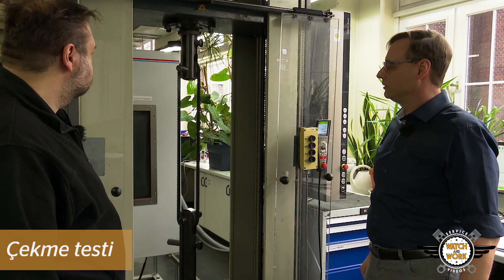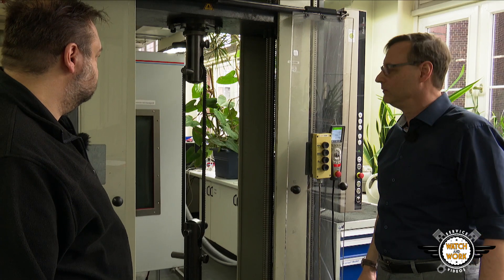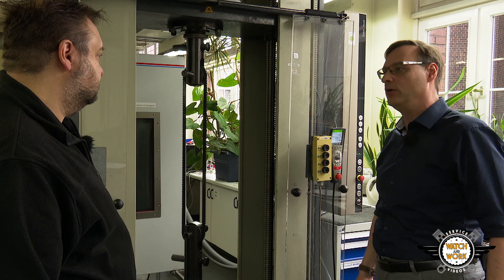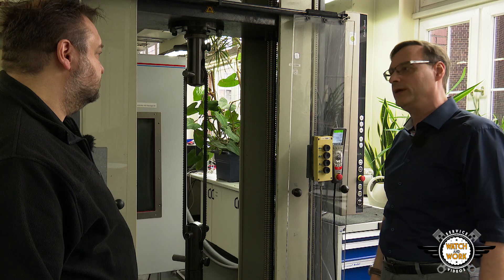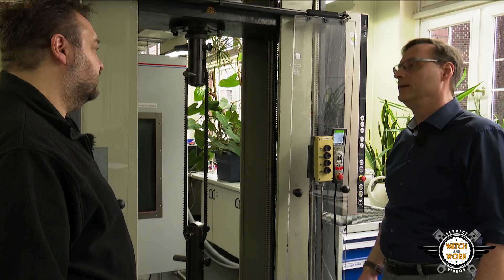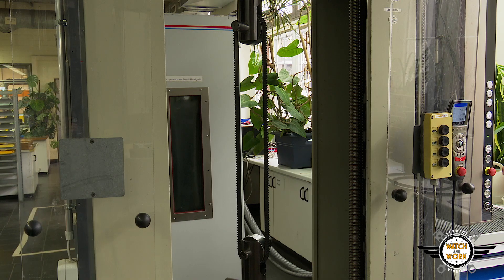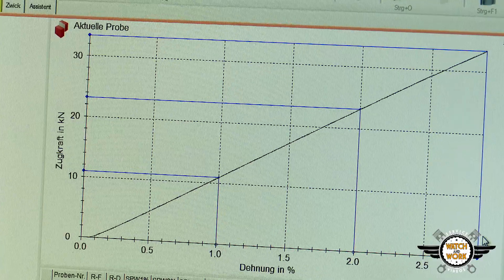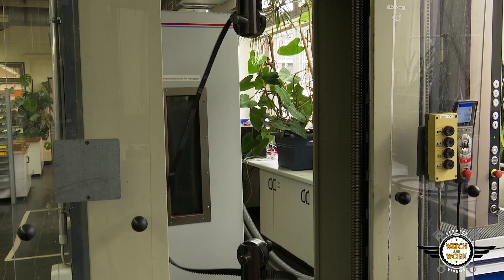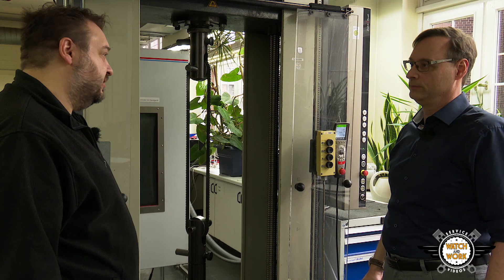This is our tensile test. The maximum tensile force our belts can withstand before they tear is one of their most important properties, and usually includes a large amount of spare capacity so that the belt drive can continue to transmit maximum power even after 10 years of use. The belts are always designed with a very large safety margin, so the belt can safely handle everything it has to go through during its lifetime. A belt normally has a tensile strength in excess of 35 kilonewtons, or 3.5 metric tons — meaning you could easily hoist a fully laden sprinter van with it.